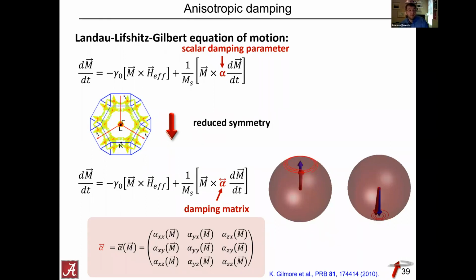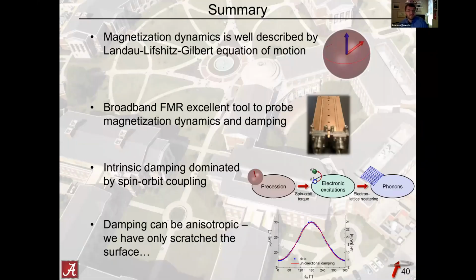So that brings me to a brief summary. I hope I showed you how the LLG equation of motion is a very suitable tool to describe the magnetization dynamics. I showed you how you can use broadband FMR to probe the magnetization dynamics and learn a whole lot more about the damping than by just measuring at a single frequency. In iron, we were able to show that the intrinsic damping appears to be dominated by spin-orbit coupling, which leads to this conductivity-like term that dominates at low temperatures, where better structural quality of your film doesn't necessarily mean a lower damping.